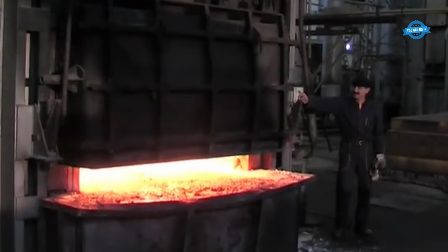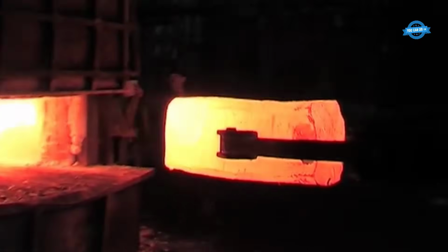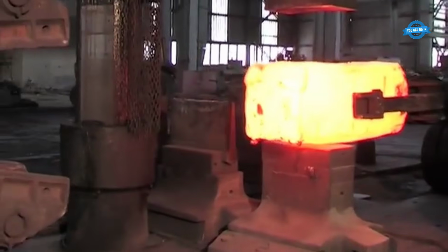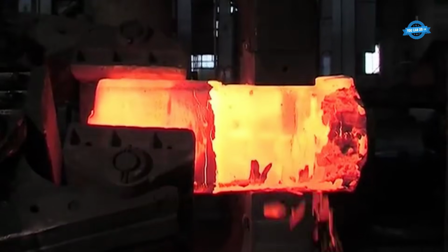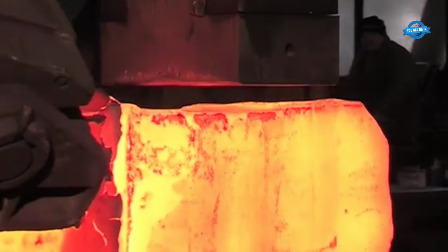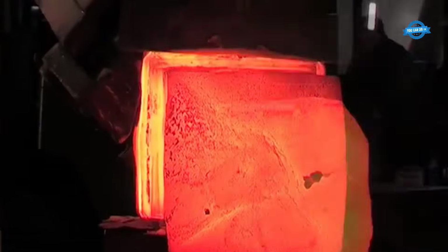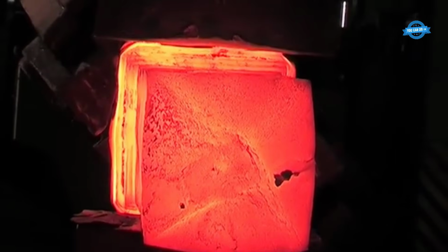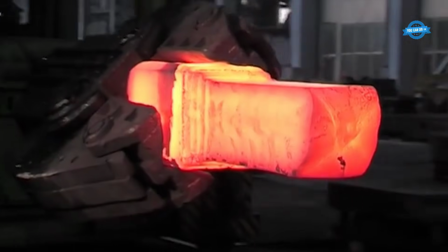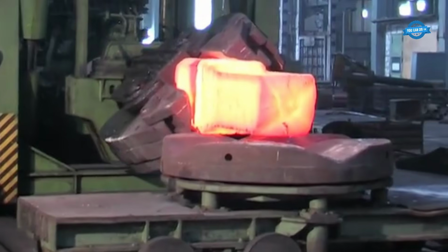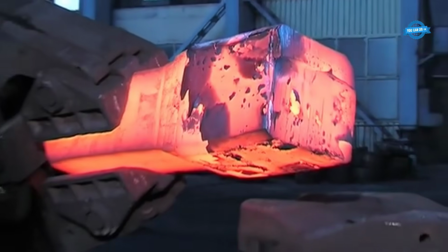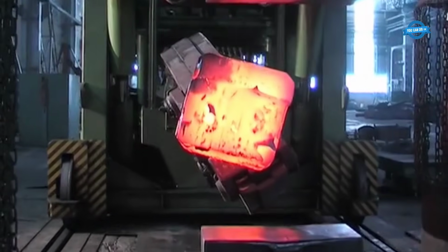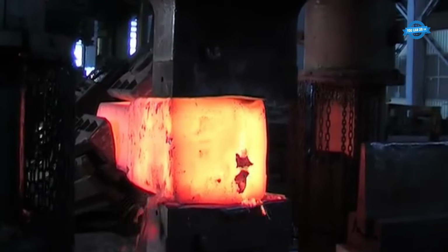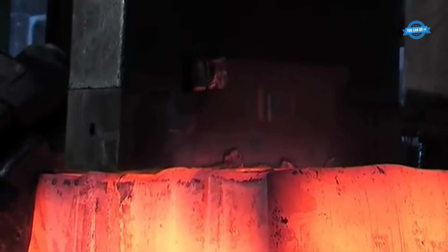The significance of large long shaft forgings lies in their installation in critical parts of machinery and their exposure to heavy loads. Consequently, these forgings must be free from defects such as porosity, segregation, and inclusions to achieve the required performance. As these forgings are typically made from ingots, which inherently contain metallurgical defects, addressing these defects becomes essential. This involves eliminating the metallurgical defects of the ingot itself, achieving a uniform fine grain structure, and ensuring a quantitative distribution of mechanical properties in the forging. The quality of these forgings not only drives industrial development but also ensures the safety of equipment operators.